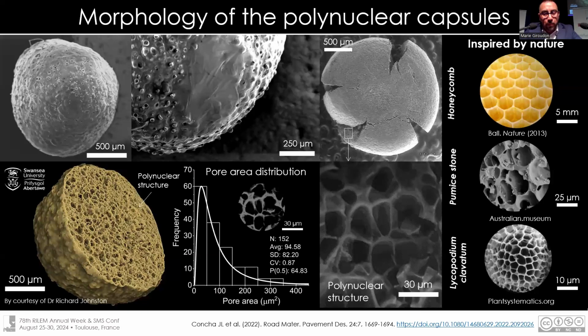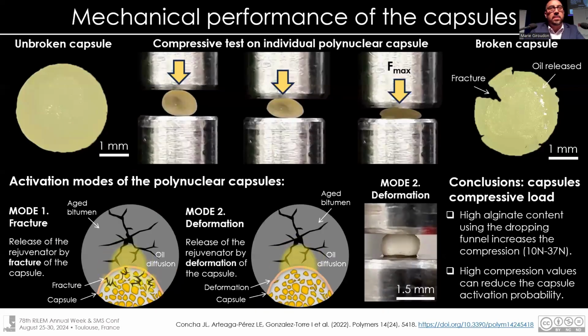The correct design of the pore morphology inside the polynuclear capsule is necessary so that the rejuvenator can be efficiently encapsulated. For example, in this slide, you can see a CT tomography of the individual polynuclear capsules. Basically, you can design in the lab artificial polynuclear capsules with self-healing purposes, inspired by nature. At the same time, these capsules need to be incorporated inside the asphalt mixture during the mixing process. For that reason, the mechanical performance of the capsule is so important.